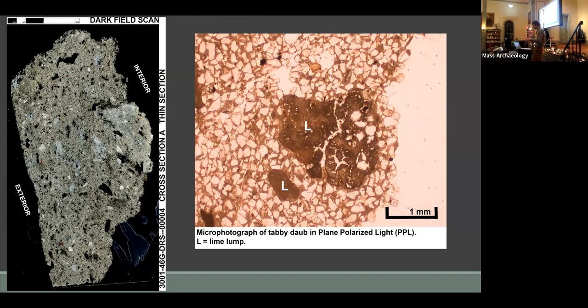There are also lime inclusions within the sand aggregate, which is basically reused lime tabby mortar, which points to them grinding up old tabby fragments and adding them to the mix, akin to grog in ceramics. And so additives and admixtures are added to mortars in small quantities to provide strength, waterproofing and durability. We don't really see these materials in tabby, although that's something that I'm investigating with the tabby daub. There are clay fragments within it. And again, that addition of clay coatings on some sand particles and some shell particles could have an effect and basically allow the tabby to gain strength in different ways.